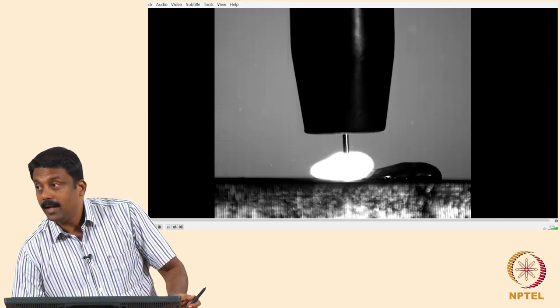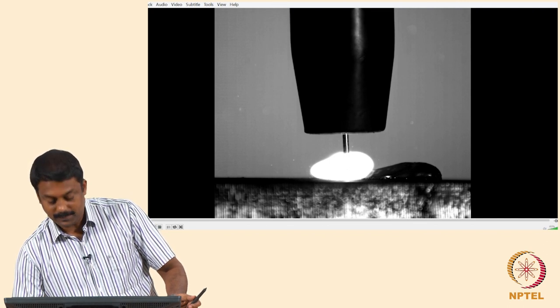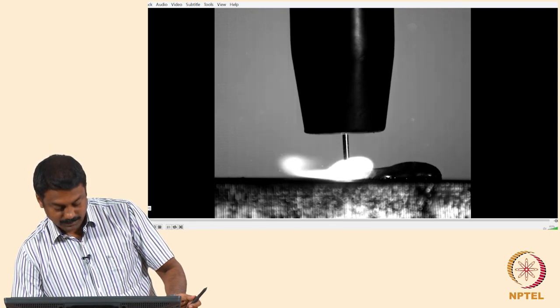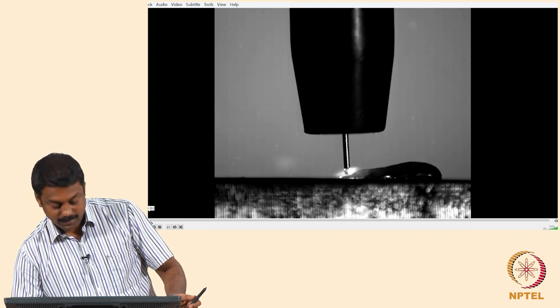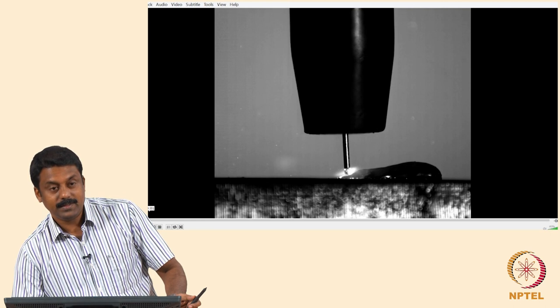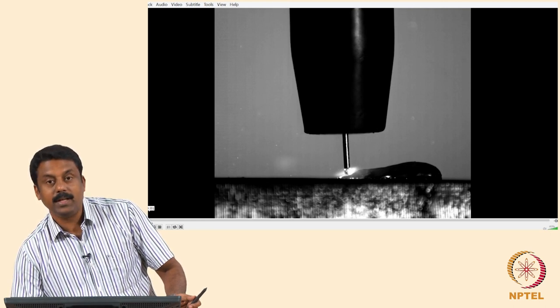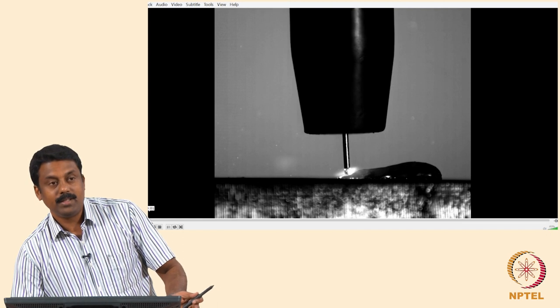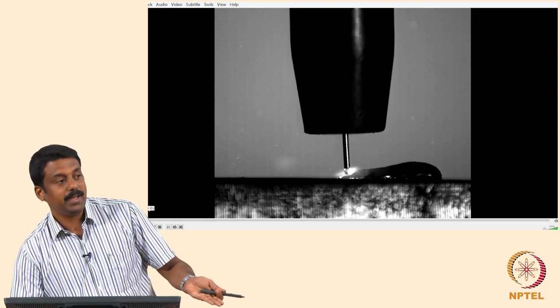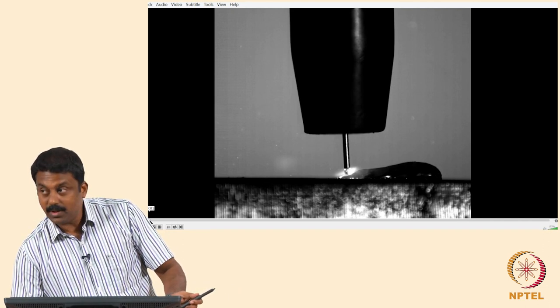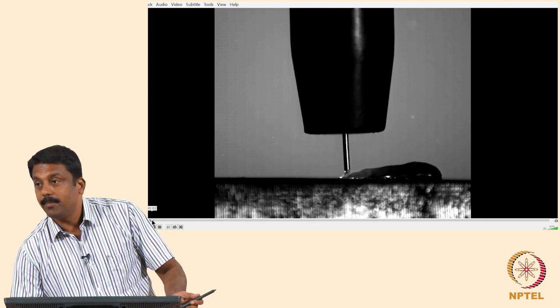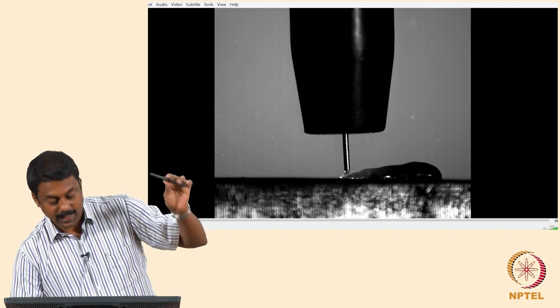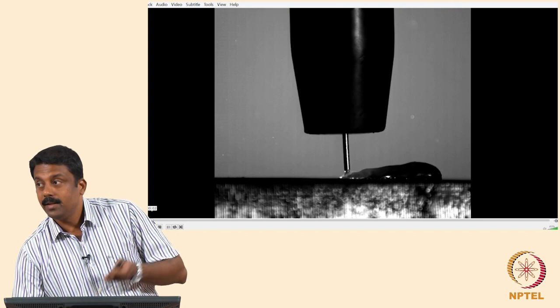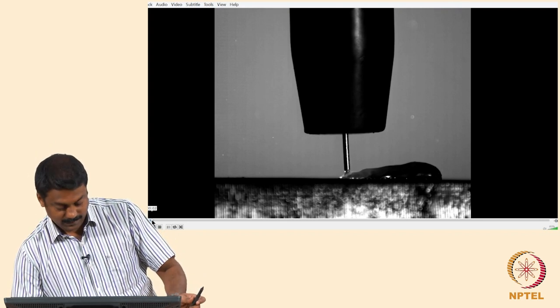Now a pulse. The droplet is molten. The tip has formed a droplet. And then you are also pushing the wire, because your feed rate is higher than the melting rate. And the moment the short circuiting event happens, the power source switches off the current. The power source can detect the short circuiting event by measuring the voltage. The moment the voltage becomes extremely small, that means short circuiting has happened, and then the current is switched off. The arc is completely gone. So now the wire can be retracted back, and during this process the surface tension of the pool pulls the droplet with its surface.